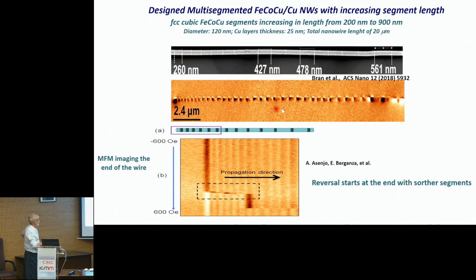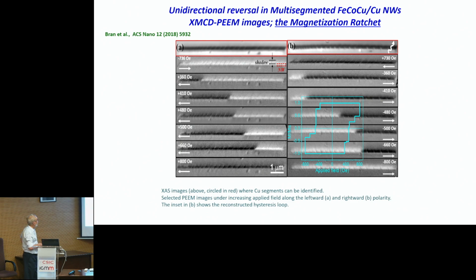This is a magnetic force microscopy image from the end of the nanowire in the remanence, and it was observed by magnetic force microscopy that the reversal of magnetization started in the end with the smaller segments. And this was confirmed and investigated even more. We were able to get more information with the PEEM images with the circular dichroism analysis. We observed what we call magnetization ratchet.